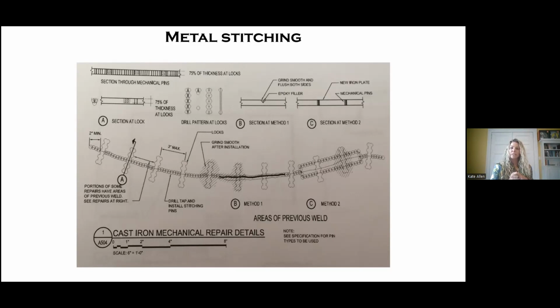What you need to know is that basically the pins are sealing the crack and the locks structurally stabilize it. The advantages to this method is you don't need heat. It's easier to perform in the field, and it's very successful compared to something like welding. It's similar to a threaded rod repair in that you're tapping a hole and you're adding a pin. It's very slow though. One man can perform an inch an hour.